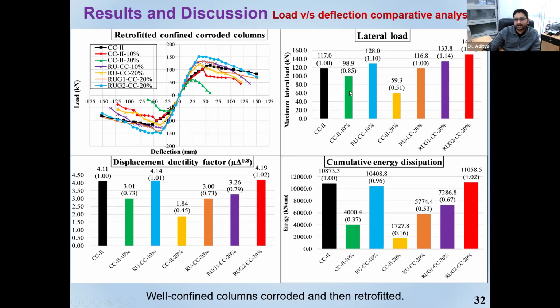Then you can see when I retrofitted this column with only UHPFRC, that's it, the lateral load capacity again increased to 128, which is even 10% higher than the control column, which seems to be fine, acceptable to us, because we have completely recovered. So even if a column has been 10% corroded, if we retrofit it using only UHPFRC, we can recover its complete lateral strength, or the lateral load capacities.